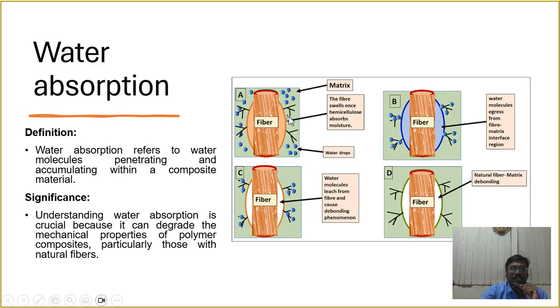This creates an effect because of cellulose. If the fiber is made up of natural fiber, cellulose is one of the materials of the fiber. The matrix may be non-absorbing of water molecules, but because of its porosity it can allow water molecules inside up to the fiber regions. The fibers may be natural fibers which have cellulose content, and they can easily absorb the water molecules. So the fiber swells once the hemicellulose absorbs the moisture. The cellulose material can absorb the moisture content and swell.